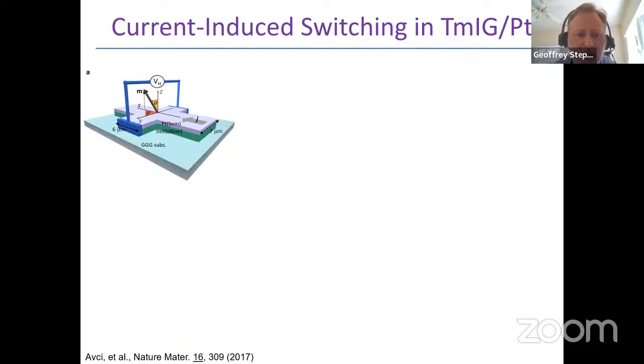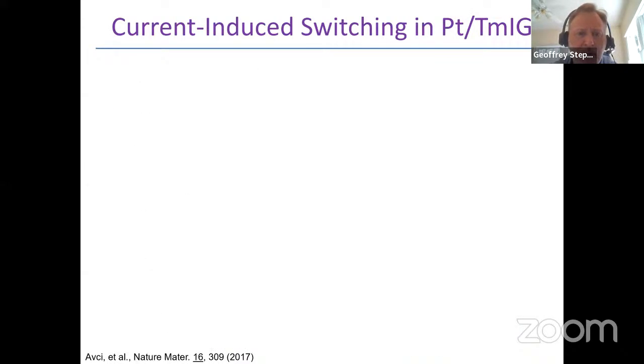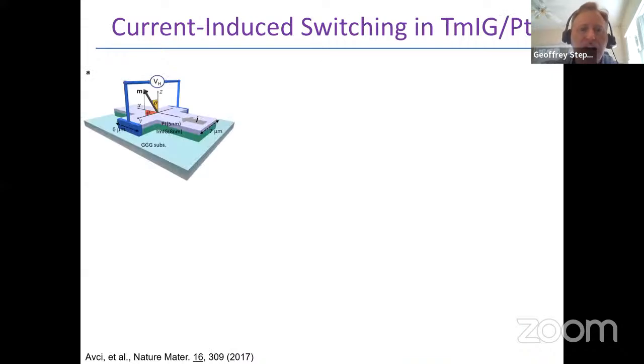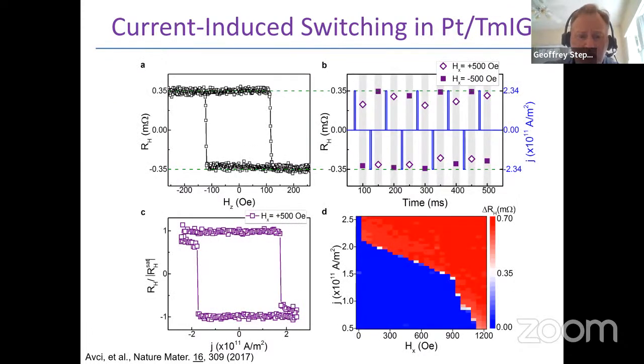We demonstrated back in 2017 that in thulium iron garnet with perpendicular anisotropy, by putting a platinum layer on top, one can use current injection to switch the magnetization in the same way as you can do it with a platinum cobalt bilayer. We've shown that this can be done repeatedly. This can be done at quite low current densities. So we know then, in this case for the first time, that you can pump enough spin current from a metal like platinum into an insulating ferrimagnet to actually effectuate switching.